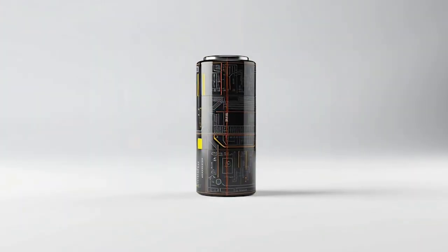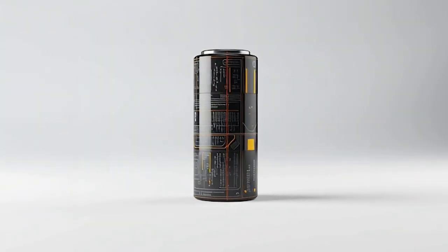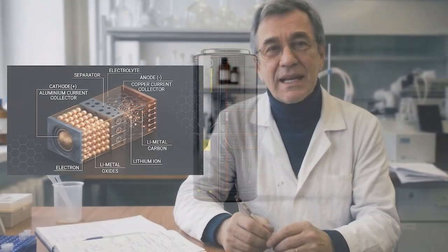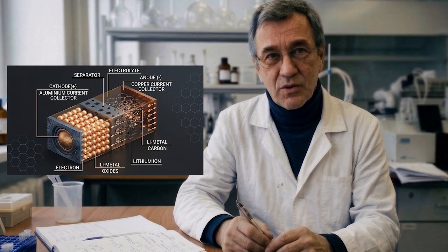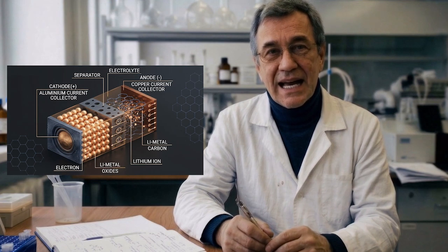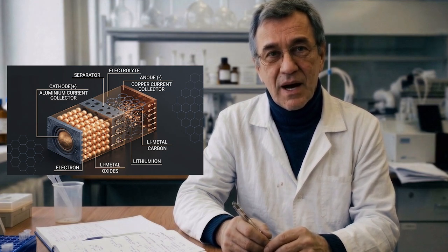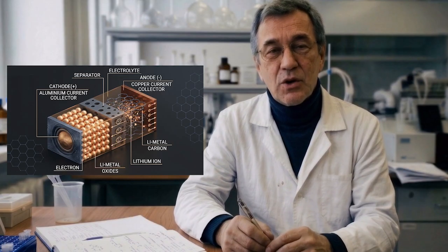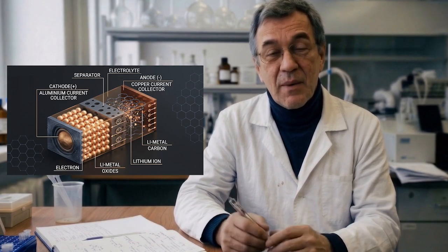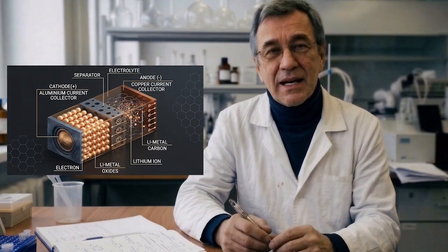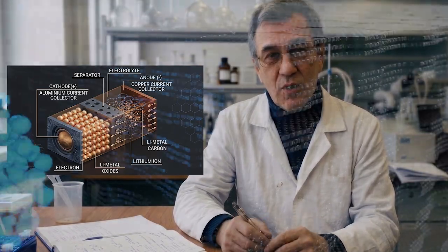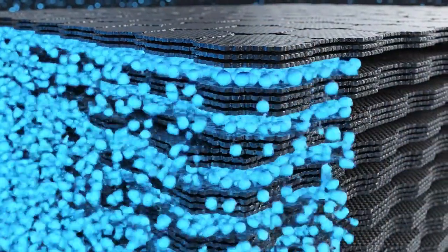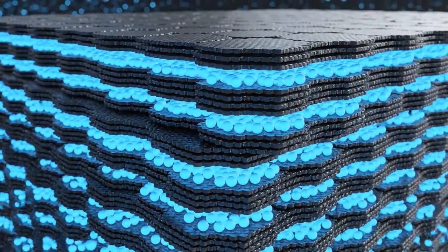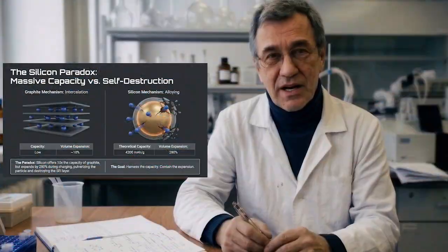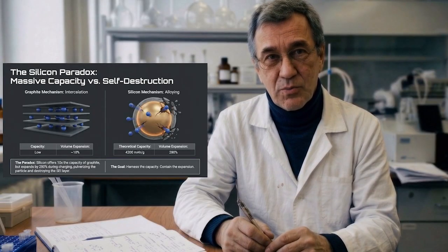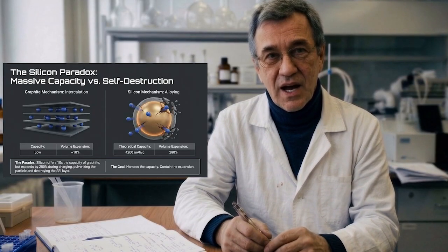Before we dive into new materials, let's briefly recall the battery's architecture. A lithium-ion cell is a tightly packed structure. It consists of a cathode, typically a lithium metal oxide, and an anode, which is our focus. Between them lies a porous separator, and the entire system is soaked in an electrolyte. During charging, lithium ions travel from the cathode through the electrolyte and insert themselves into the anode structure. Graphite, with its layered structure, is excellent at this. The ions slip between the layers, causing only a 10% expansion. This process, called intercalation, is highly reversible, which is why graphite anodes can last for hundreds of cycles.